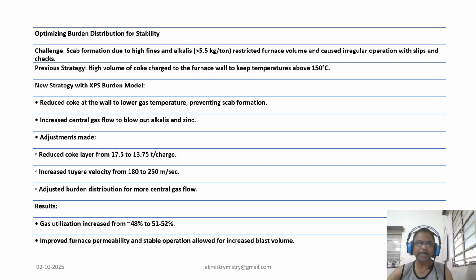One of the biggest operational challenges was the formation of scabs, or buildups, on the furnace wall caused by high levels of fines and alkalis in the raw material. The old strategy involved charging a high volume of coke to the furnace wall to keep temperature high. However, the XPS burden model enabled a completely new approach. The new strategy reduced coke at the wall to lower the gas temperature, which prevents scabs from forming. Instead, gas flow was directed more toward the center to blow out the harmful alkali and zinc. This involved adjusting the coke layer, increasing wind velocity, and optimizing the burden distribution profile.